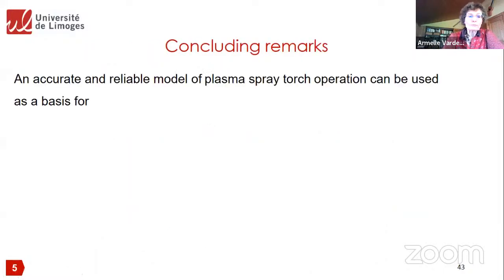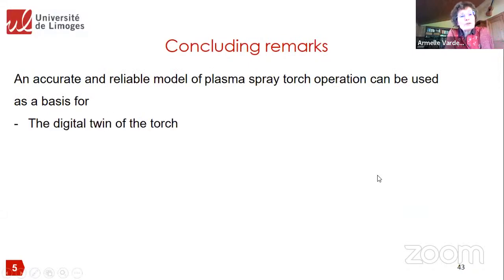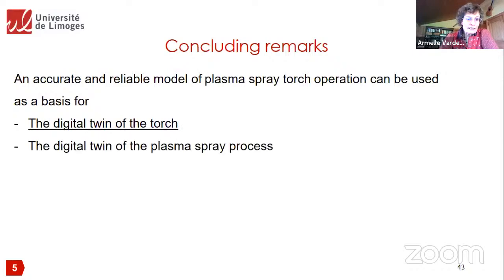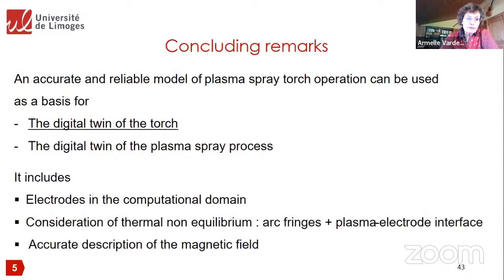So as a conclusion, an accurate and reliable model of plasma torch operation can now be used as a basis for the development of a digital twin of the torch first, because it's important to have a digital twin, not only of the whole spray process, but also of the torch itself. This is very important, in particular for the manufacturers of the torch, like Oerlikon Metco or Metec. And it can also be used as a basis for the mechanistic model of the plasma spray process. But for that, it should include the electrode in the computational domain.